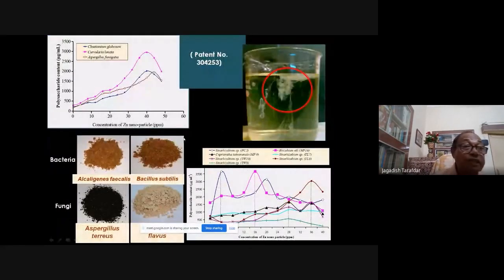Now, what do nanoparticles do? They can prepare polysaccharides, nano-induced polysaccharides. If we apply nanoparticles to polysaccharide-producing organisms, such as fungi and polysaccharide-producing bacteria, for example zinc nanoparticles, you see the basic polysaccharide production capacity improves 10 to 12 times. We have developed a method, and this is my patent of this method,